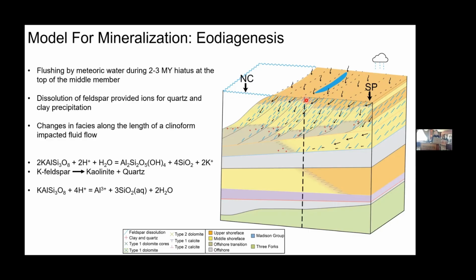So we think that as feldspar dissolved, some of that was transported out of the system in more of an open diagenetic scenario, as a result of the high amount of fluid flux that was being experienced as the meteoric water kept infiltrating through time. And this is, I should say, relatively limited to the upper portion of the Sappington. We don't really observe this nearly as prevalently in the bottom portion of the Sappington. And it seems that some of the facies transitions along the clinoform might have imparted some changes in fluid flow as well, where the coarser grained, higher permeability facies in the upper shoreface probably had higher fluid flux than what we saw further down in the toes of the clinoforms in the offshore transition facies.